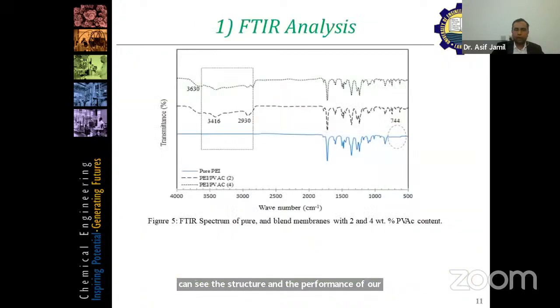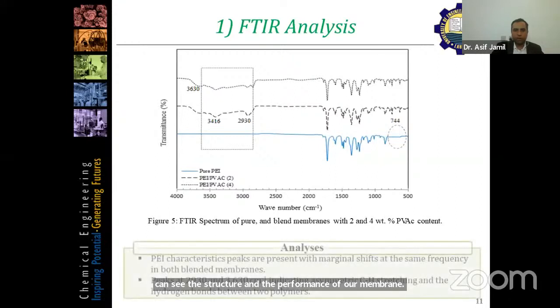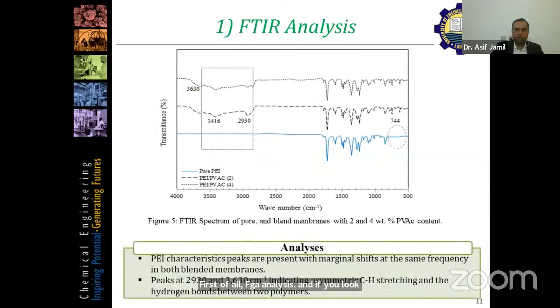First of all, FTIR analysis. If we look at the blue line here, which is pure polyetherimide, we can see its curve, but when we add polyvinyl acetate, the curve is different. Especially we have two different peaks at 2930 and 3416, which show that there is CH bond stretching at this point. So it means there is some kind of bond formation between the two polymers.